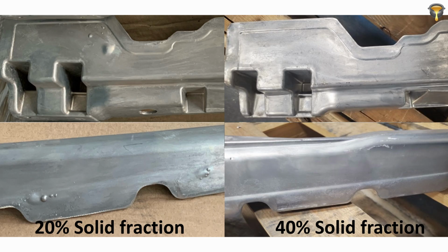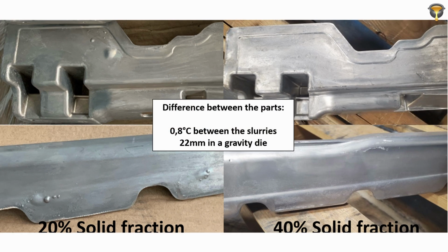Absolutely, and we can show you the pictures again and let you guess what is the temperature difference in that same slurry between 20% solid fraction and 40% solid fraction. We will give you a few seconds of time to think about a number. You got your number? All right, then I will tell you the number. It's 0.8 degrees Celsius between these two slurries. And that's with the same batch. If you have a variation from one melt to another melt, the changeover in the liquidus temperature is way bigger than that change in slurry.